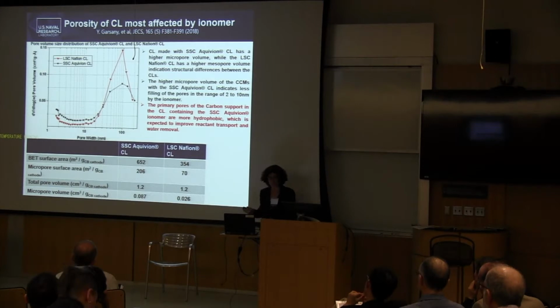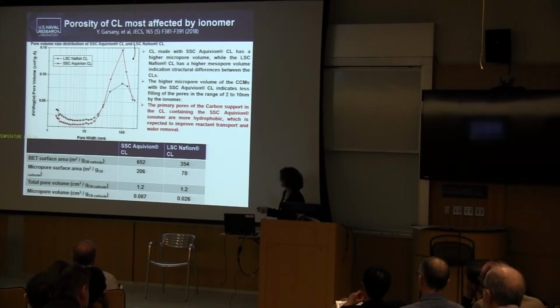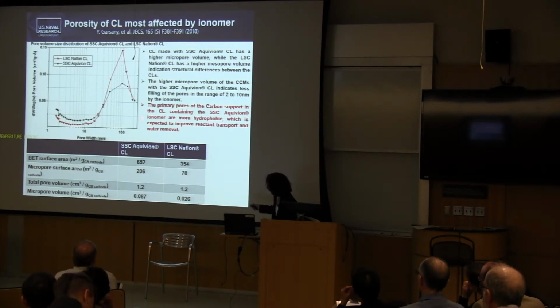Before we were running to the synchrotron, we were doing computed tomography, and one of the women in our group said, I'm going to go do BET. I'm like, well, that is never going to work. Well, it works pretty well, and it's cheap, and most chemistry departments have one. But look at what a difference it is. It's changing here, more pores in this very small pore region for the Aquivion, and fewer up here.